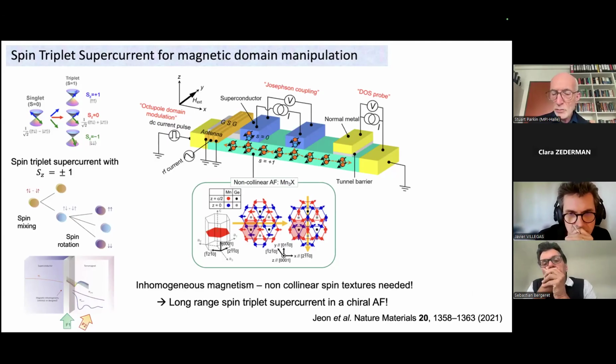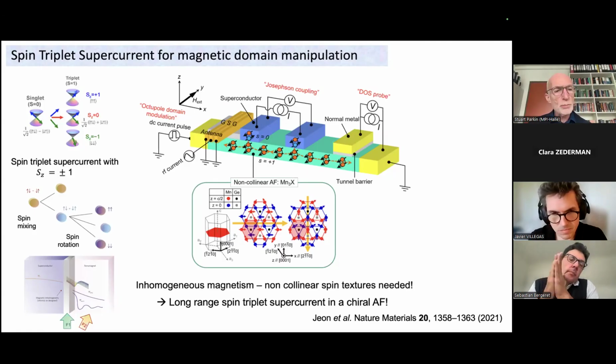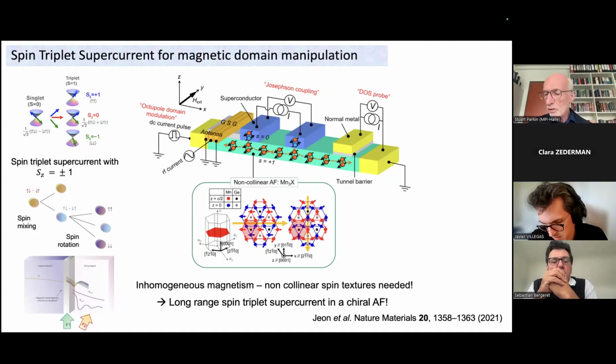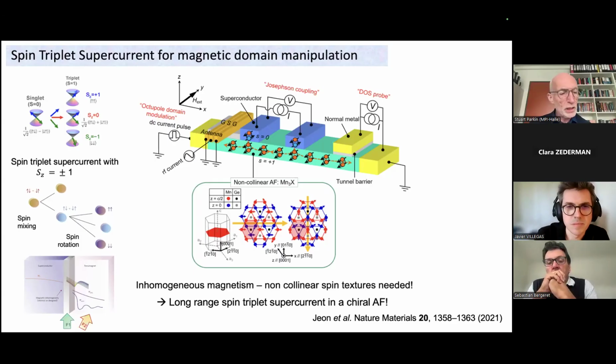And so we argued we could see long-range spin triplet supercurrents in this chiral antiferromagnet. On the left-hand side, you can see this concept: you take a singlet superconductor, you form a triplet pairing, and then the non-collinear magnetization allows spin rotation and long-range spin triplet supercurrents. So we think this is a very interesting means of generating spin triplet supercurrents.